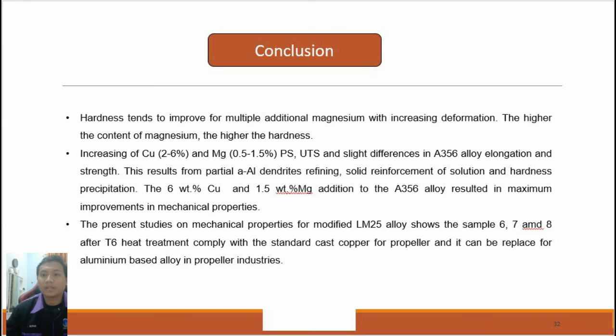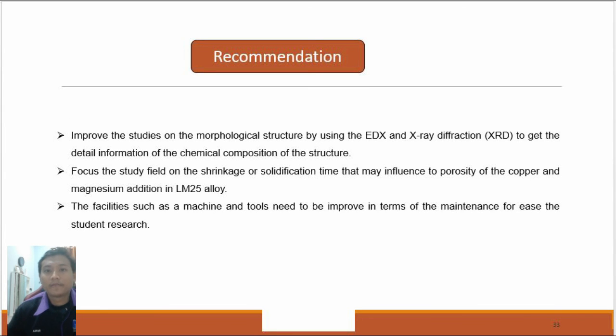The present study on mechanical properties of the modified LM25 alloy shows that samples 6, 7, and 8 after T6 heat treatment comply with the standard cast copper for propellers, and can replace it as an aluminum-based alloy in the propeller industry. For recommendation, the studies on the morphological structure need to be improved by using EDX and X-ray diffraction to get detailed information on the chemical composition of the structure. Next, focus the study on the shrinkage or solidification time that may influence the porosity of the copper and magnesium addition in LM25 alloy.